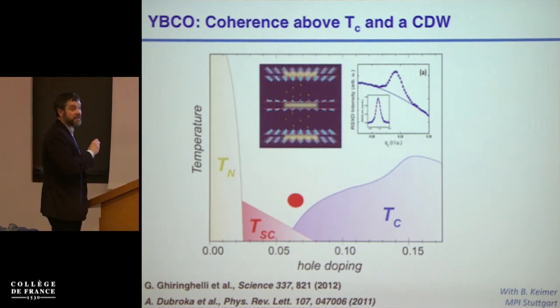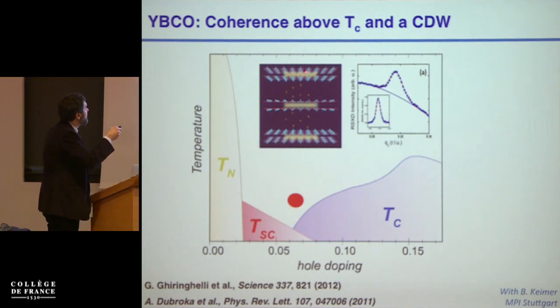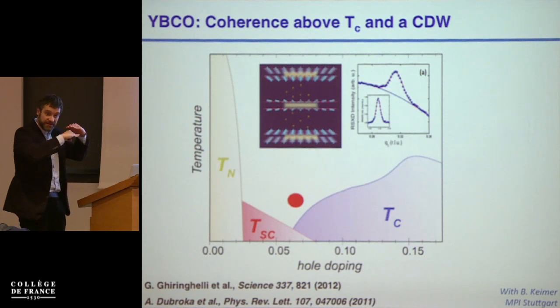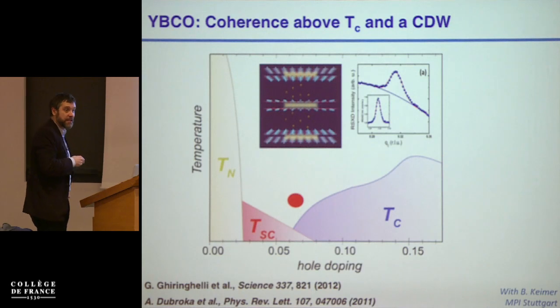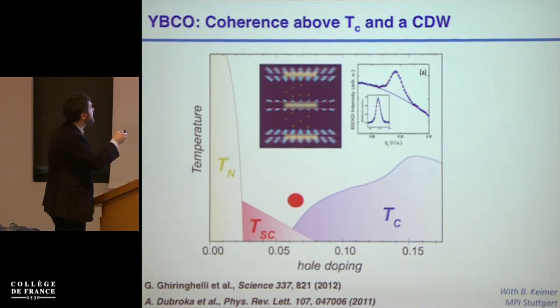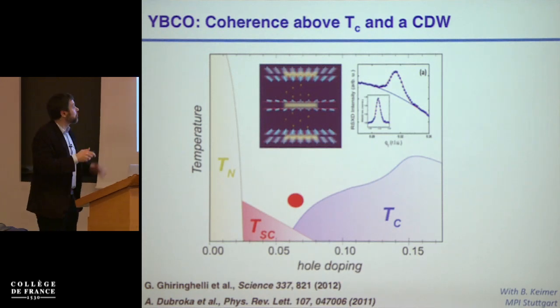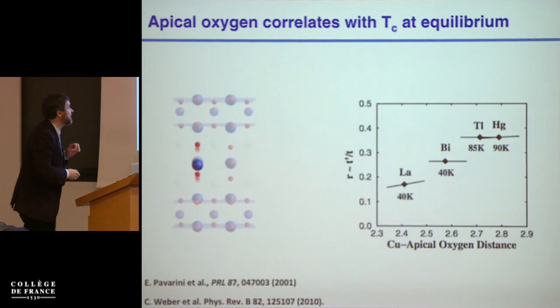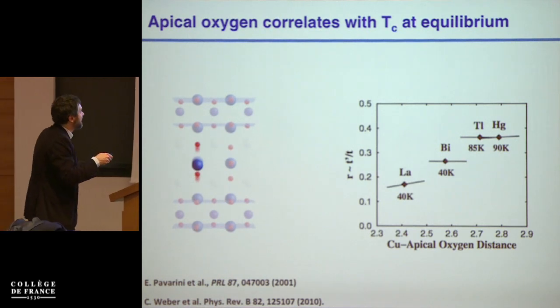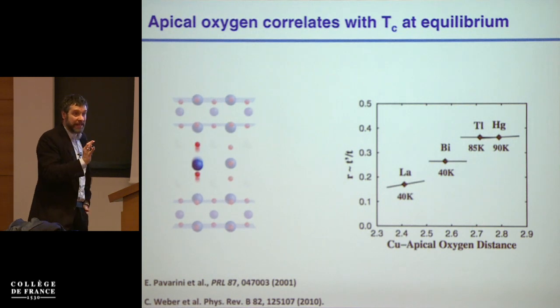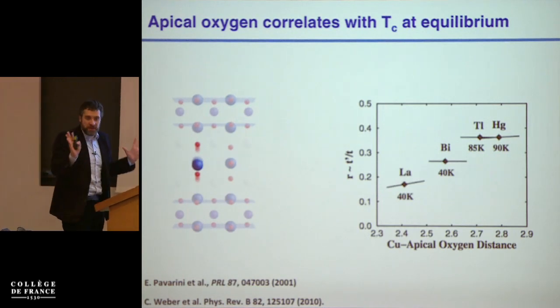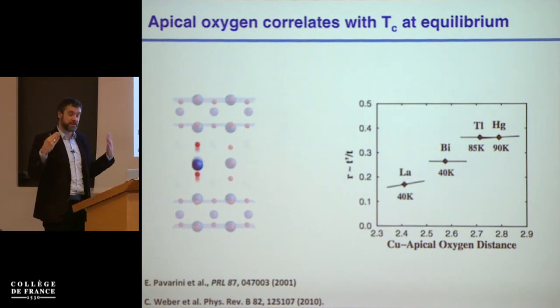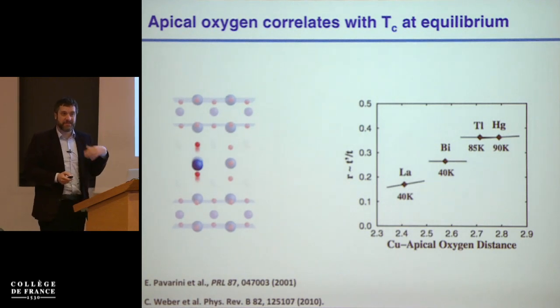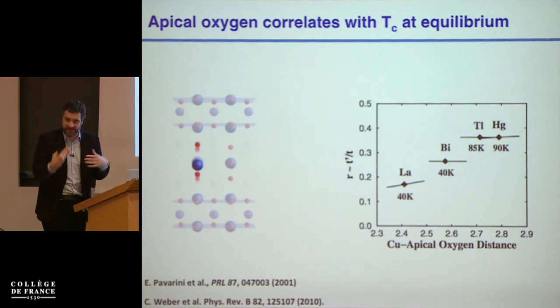And the second thing are these very beautiful optical experiments that are suggestive of pre-existing pairing or pre-existing interlayer tunneling fluctuations between the bilayers. So there is some degree of evidence, at least, in the optical spectra that one could think of a precursor superconducting state that comes from the appearance of a mode that would in principle be related to these fluctuations between the layers. The other thing that one knows about this compound is that it's quite well established that the position of this specific oxygen mode appears to correlate strongly with the TC in all cuprates and in YBCO as well. So without really knowing what we're doing, we could decide that we could take YBCO, go to temperatures either below or above TC, excite this apical oxygen mode, and then decide that we want to either see a reduced superconducting state or an enhanced superconducting state.